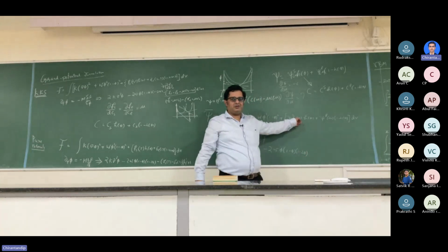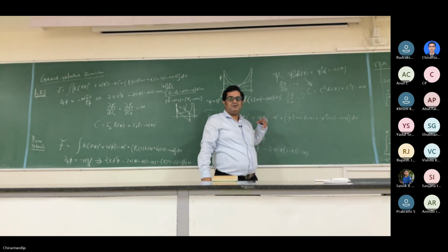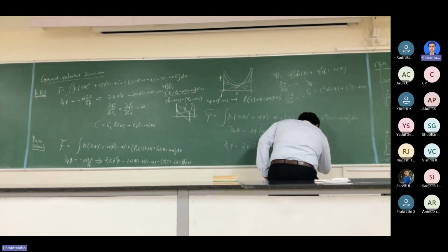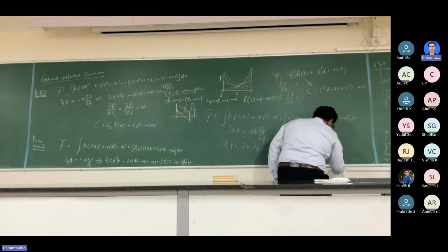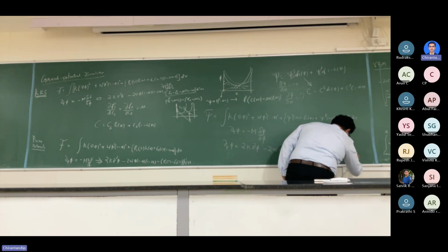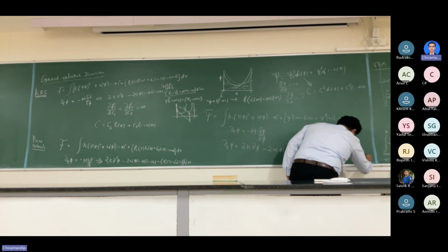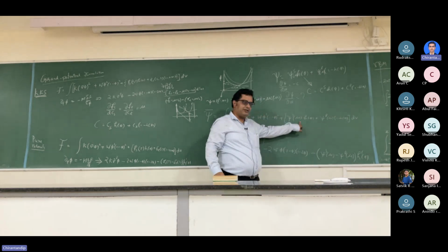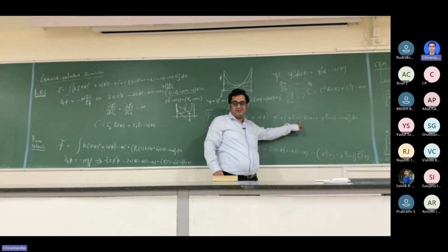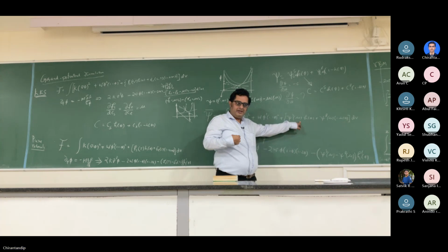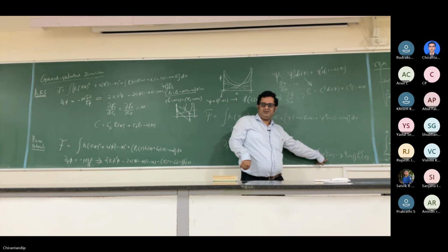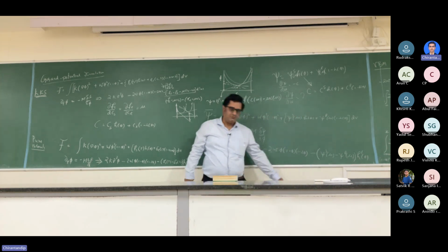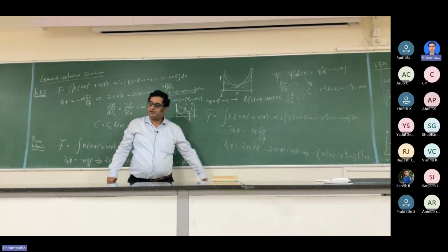So who will tell me what the variational derivative of this will be? Remember, this derivative when I am taking, it is at a constant mu because I want to have a separate equation for it. Okay? So mu and phi are now my independent variables. So when I take this partial derivative, it is at a constant, right? So psi s of mu minus psi l of mu, h prime of phi. This is your evolution equation for phi.